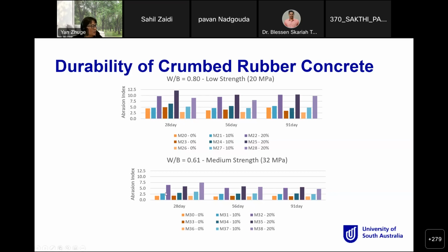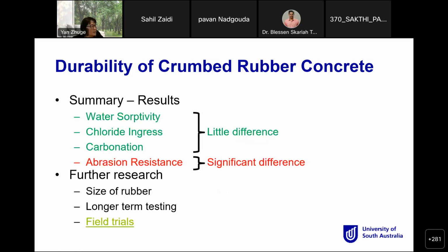When you have higher strength, you get probably similar trends. When you have 10% of rubber, still okay. But when you use 20% of rubber, there is a pretty big increase in abrasion index. So that is a negative point about durability performance. Okay. So now is the summary of our durability tests for crumb rubber concrete. The water sorptivity, chloride ingress, and carbonation all show little difference. So the performance is very similar to the normal concrete. But for abrasion resistance, there is a significant difference.